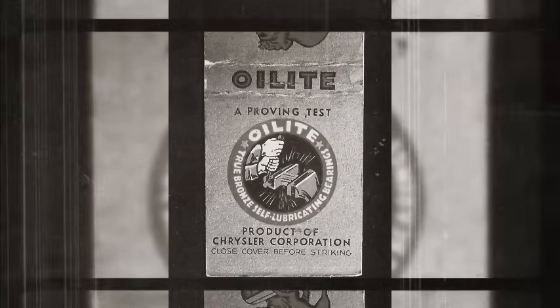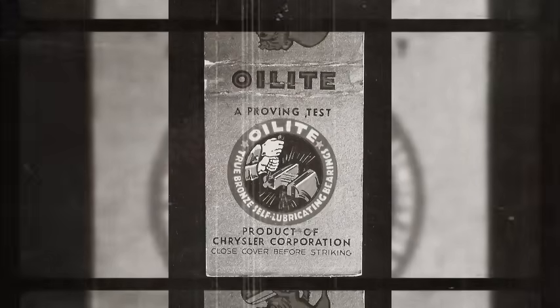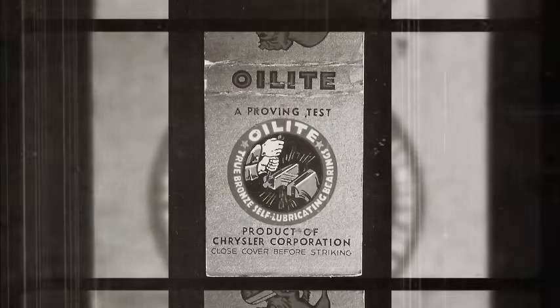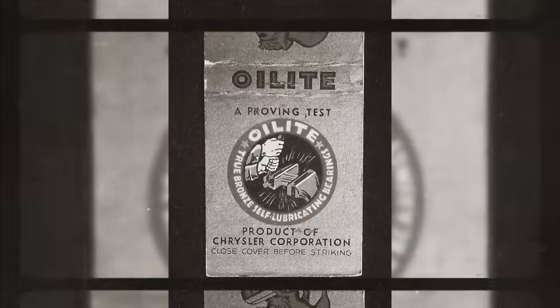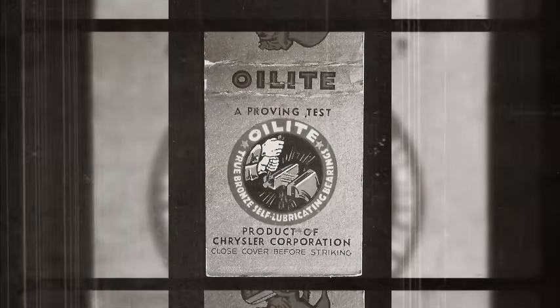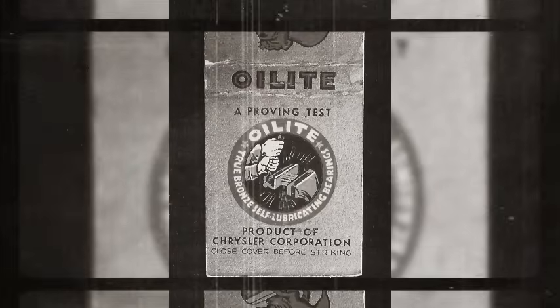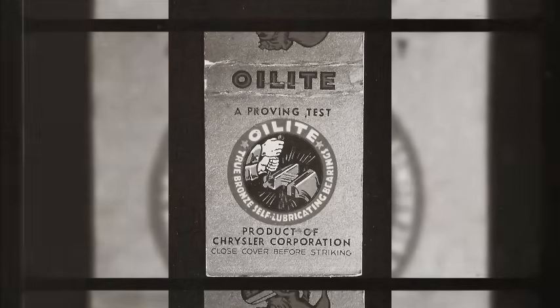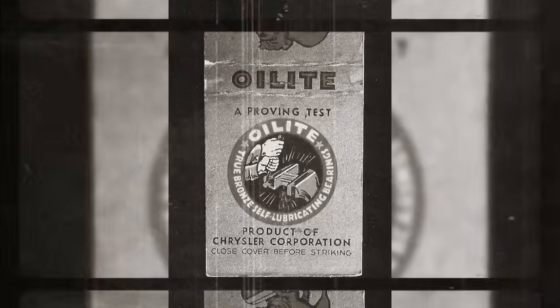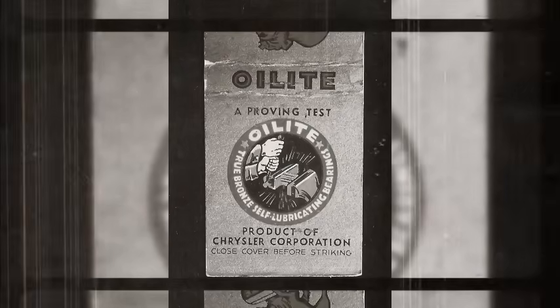Operating principle: when a shaft rotates in an Oilite bearing, friction generates heat. The heat causes oil viscosity to decrease, so the oil becomes more fluid, and the metal to expand microscopically, pushing oil toward the surface and causing it to migrate to the bearing/shaft interface. When rotation stops and the bearing cools, capillary action pulls oil back into the pores. The bearing appears dry externally but remains fully oil-saturated internally. This cycle could repeat thousands of times over years of operation without the bearing running dry.